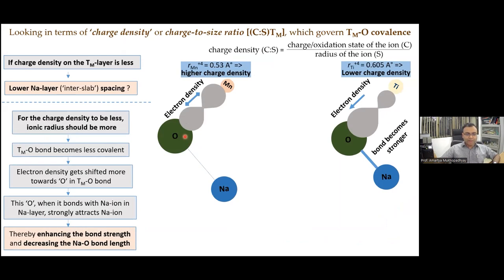If we revisit the structure of the layered transition metal oxide, we have the oxygen ion, which is bonded to a sodium ion on one side, that is the sodium interslab space, and transition metal on the other side, that is the transition metal layer. Now, the sodium-oxygen bond is predominantly ionic, having predominantly ionic character, and we feel that not much can be done to that bond because it's an ionic bond.